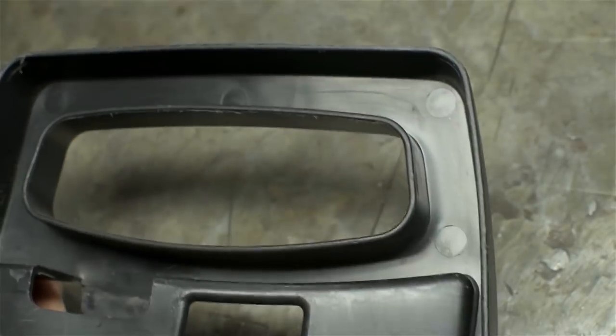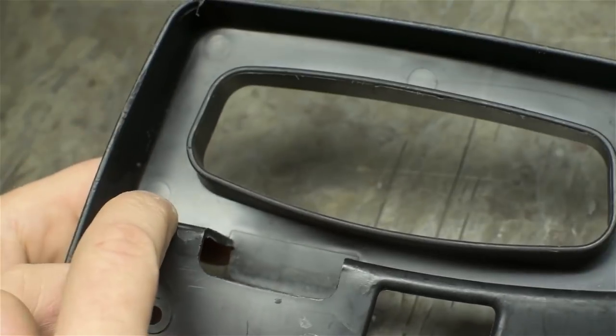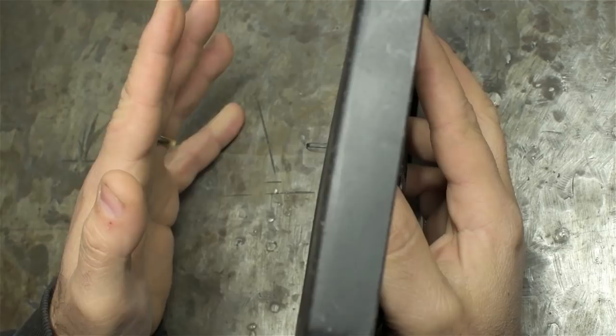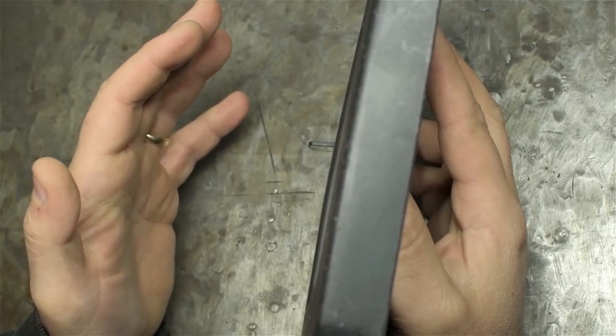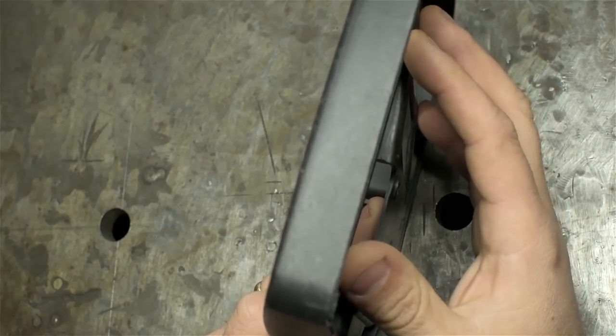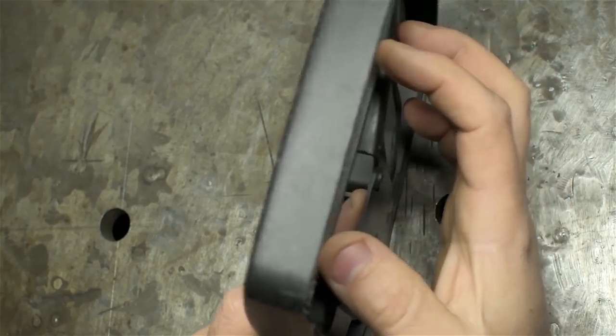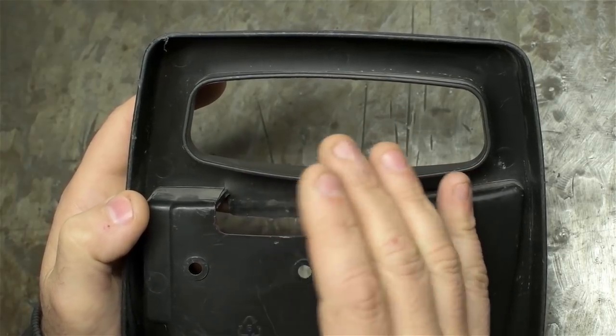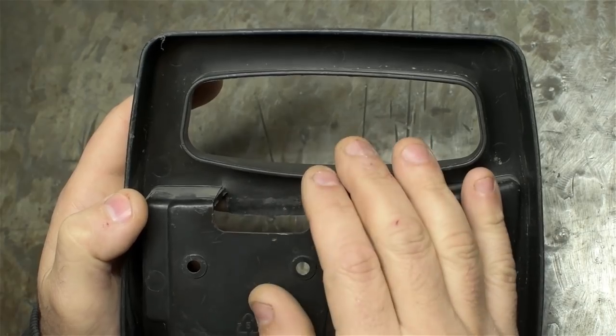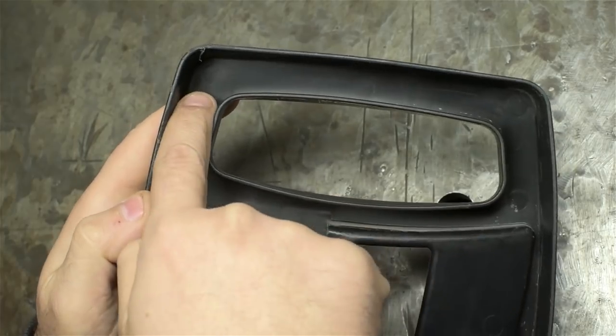And since we're taking the tour here, this won't be too relevant to the valve I don't think. But just in case, you can also see where the ejector pins were on this part. See those little circular pads in there? After this part's been injected and the tool opens, the part will stick to one half of the tool halves. Kind of like peanut butter in the roof of your mouth. Ejector pins, in this case, are some kind of ejection feature is built into one half of the tool. So when the mold opens, the part has cooled down, the pins come through the face of that tool and bump the part off. Again, since those ejector pins in this case are a separate piece of steel with some tolerance between it and the mold half they live in, and the fact that they're pushing off on probably a pretty warm part, we see evidence of where that ejection happened.